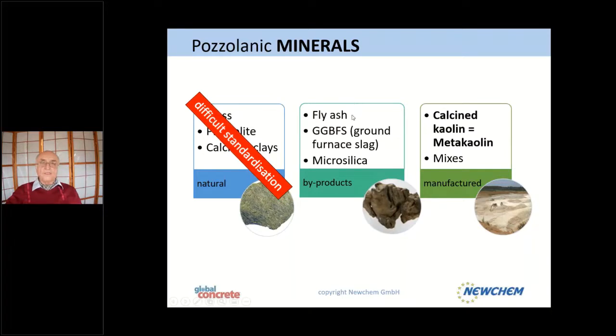As I told you, we started with fly ash, which is not really around anymore, and much more. We have heard in your conferences that slag is also decreasing a lot, and microsilica is the same. So slowly these materials are in short supply. In any case, there are not enough materials around to really modify the whole cement industry.